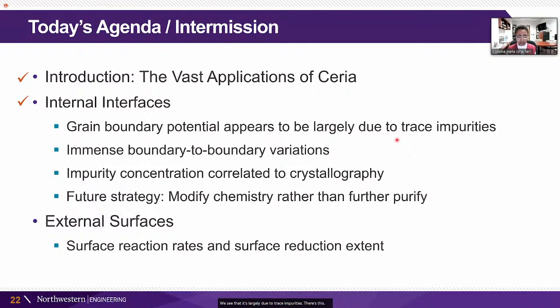There's this immense variation from boundary to boundary, and this impurity concentration is correlated to the nature of the crystallographic relationship between the two grains. And that means that in terms of the future strategy, we want to modify the chemistry by adding species like calcium to mitigate the charge rather than trying to purify further beyond 10 ppm. That, as I said, is cost prohibitive. So that's, again, our story on the internal interfaces.